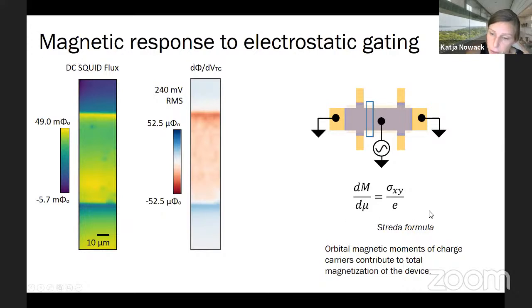And this is true in the quantized regime, but this is also true while you're within the band of any conductor. Essentially what this reflects is that the orbital magnetic moments of the charge carriers contribute to the total magnetization of the device, and their contribution varies as we vary the chemical potential. And so here we have again the DC flux image, and next to it is plotted the flux signal that's associated with the small wiggle that we apply to the top gate. And we do clearly get a magnetic signal.